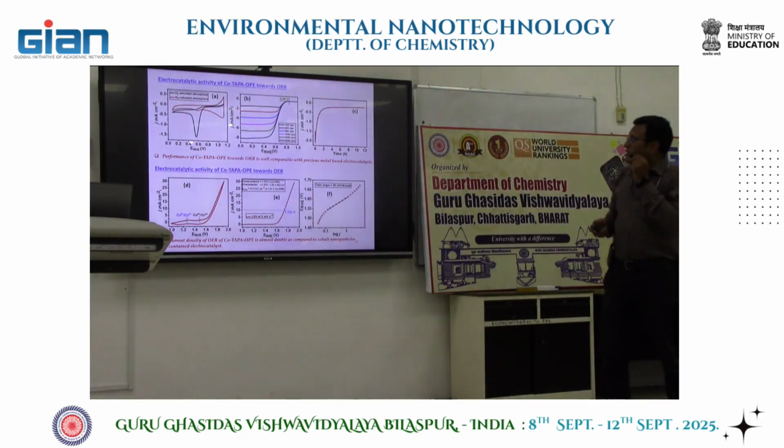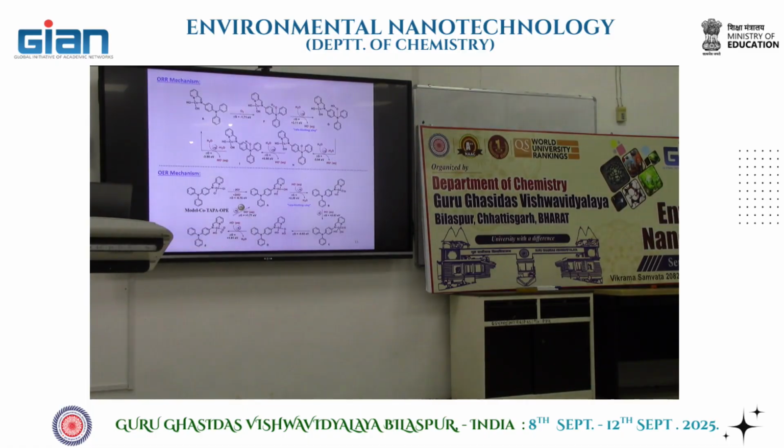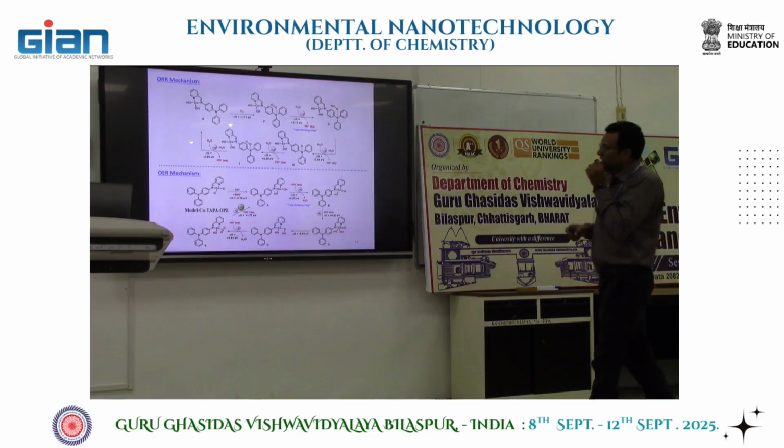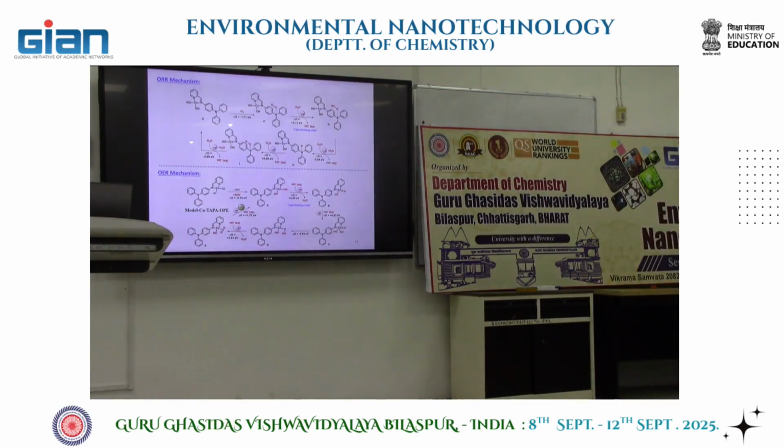Okay. So we found a material which is having both the individual properties of oxygen reduction as well as oxygen evolution in such a way that it is stable now, it is having sufficient doping and nice performance of ORR and OER. Now once we elucidated the mechanism, we found that for the ORR only the nitrogen of the triphenylamine is responsible.